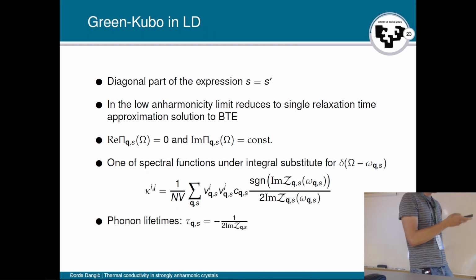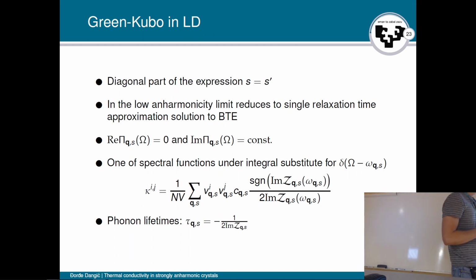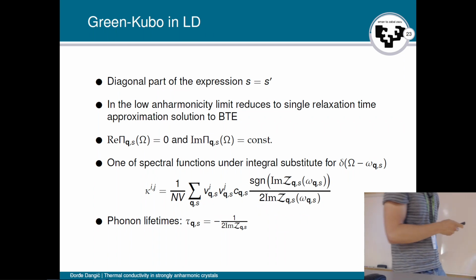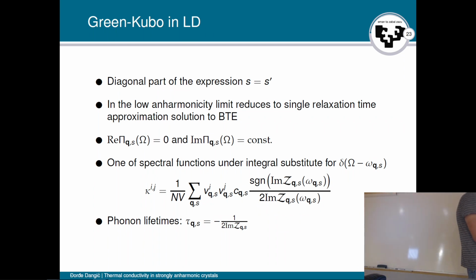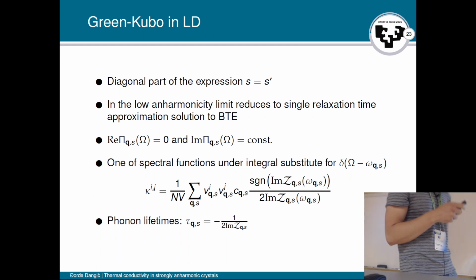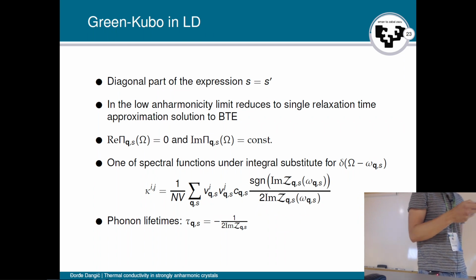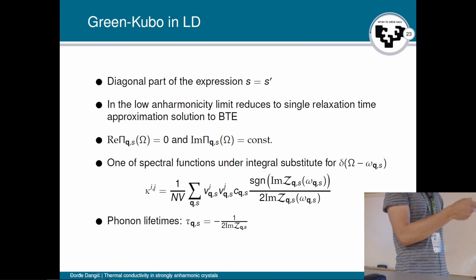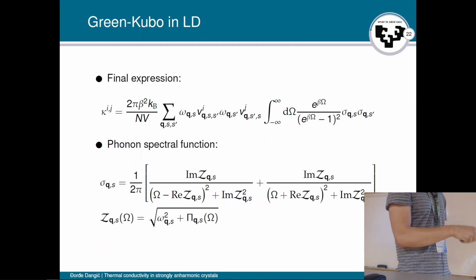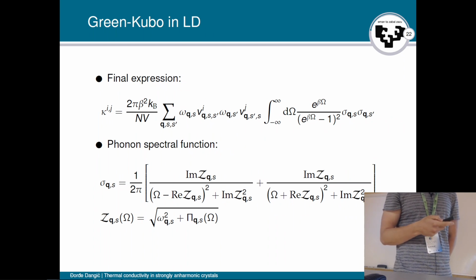So what do we mean by the low anharmonicity limit? I will refer to it as a situation where the real part of the phonon self-energy is zero, so you don't have the shift of the phonon quasi-particle energy. And then the imaginary part of the phonon self-energy is a small constant number. So you lose the dependence on omega, and if we lose the dependence on omega, obviously, we get that our spectral functions are just Lorentzians.